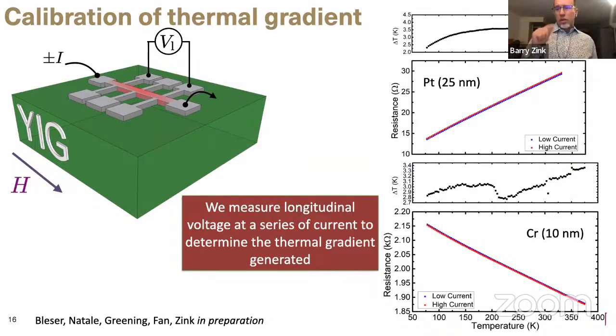The other thing that's really nice about this is that it gives you a much clearer understanding, although still maybe not a perfect understanding, of what the actual thermal gradient you generate in the spin-Seebeck experiment is. It turns out that the spin-Seebeck experiment is great. You can almost always get a signal when you slap platinum on top of YIG and get it hot somehow. But to get it quantitatively correct is a whole other ball of wax, because you really need to determine the actual thermal gradient, and that gets a little bit hard.